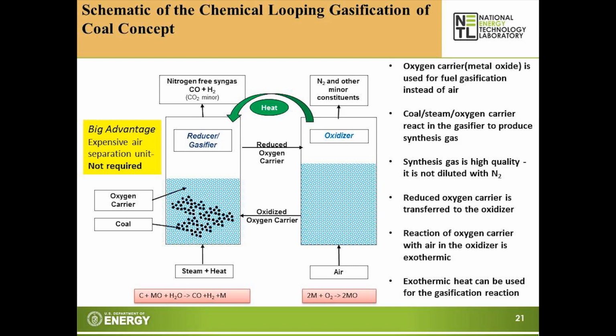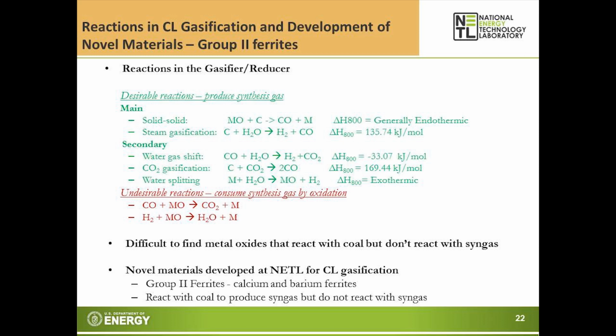So this is a big advantage: we don't need an expensive air separation unit to produce oxygen for the coal gasification process, to produce syngas free of nitrogen. And this concentrated stream can be used for chemical production. Now after the reduction, the reduced oxygen carrier is transferred to the oxidizer. The air is introduced, and this oxidation reaction is exothermic, generates heat, and that can be used for the reduction or the gasification process. However, this process is very challenging.